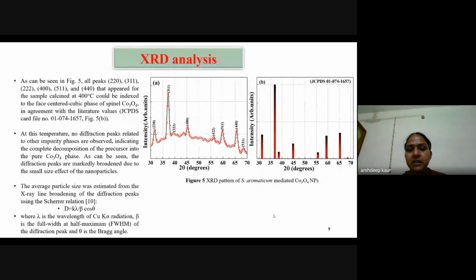This is the XRD spectra of the obtained particles. As we can see in figure 5A and 5B, the peaks in 5A are identical with the JCPDS card number, which shows that no diffraction peaks related to other impurities were observed, indicating the complete decomposition of the precursor into the pure Co3O4 phase. The average particle size was estimated from the X-ray line broadening of the diffraction peak using Scherrer relation.